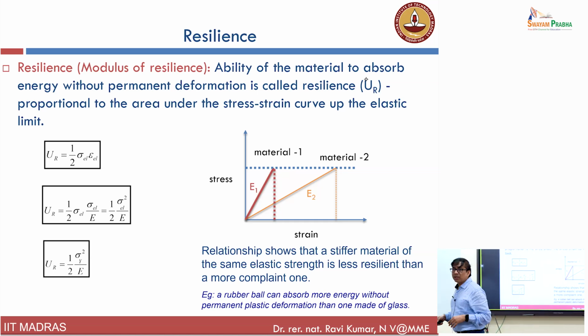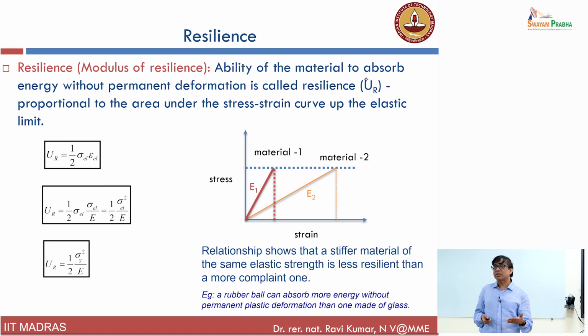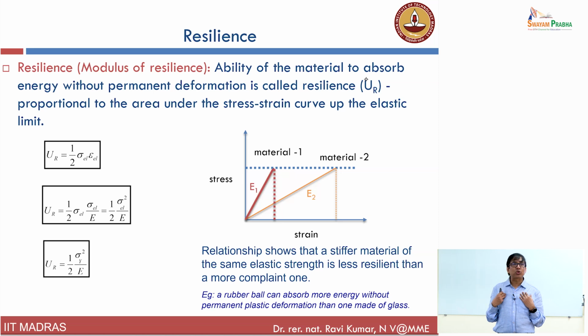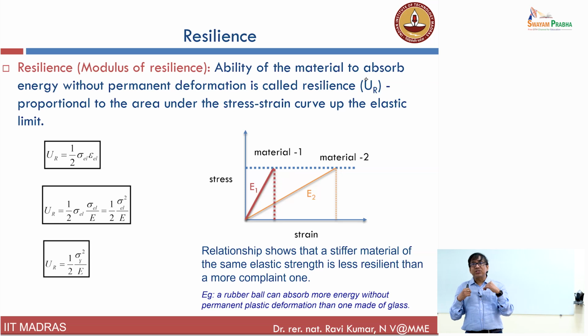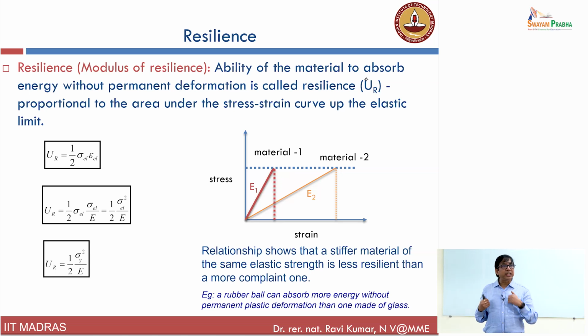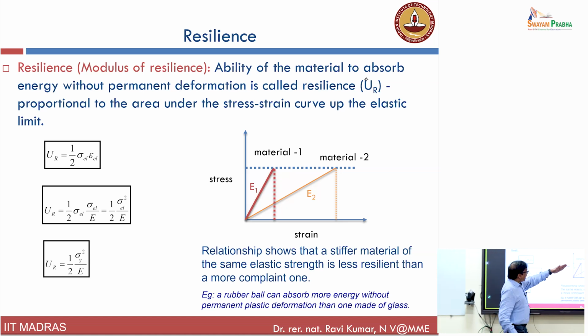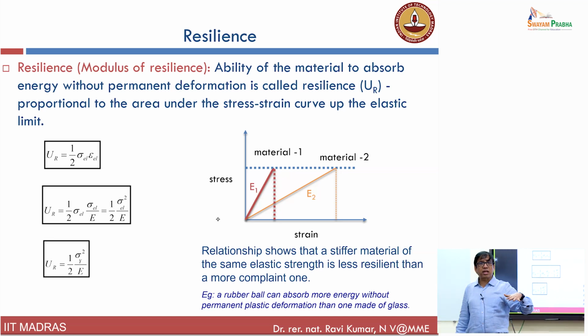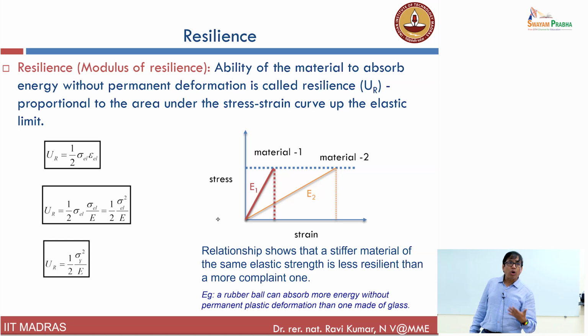I used to show this example particularly in the context of bulk metallic glasses, which when I was a student, people used to make only as ribbons. And now bulk metallic glasses are used in tennis rackets. They are used for energy absorption applications and so on, because bulk metallic glasses have very high strength as well as very high ability to absorb energy and give back. And when any material can absorb energy and give back, that is a highly resilient material, and you can calculate it very easily. The area under the elastic stress-strain region is a measure of how much energy it can absorb and give back. That is called resilience, and that's a very important one.